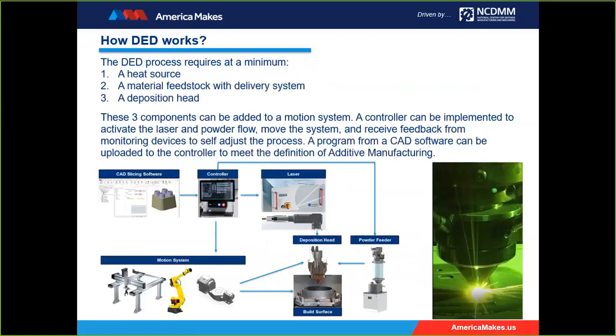A little bit more about how it works. Again, I talked about some of this on the prior slide, but you need a heat source, which we use a laser for, and then you also need the material feedstock with delivery, and then a deposition head. These key components are added to a motion system and a controller, and that's integrated with a laser and powder feeders in order to deposit material and move the head and the part where you need it to be in order to achieve your desired end geometries.